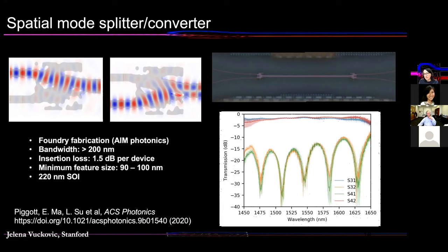When we received chips from the tape out and measured, we saw 3 dB loss total. So 1.5 dB per device. And again, the discrepancy comes from the fact that minimum features in a foundry were about 100 nanometers and not 80 nanometers the way we designed. But nevertheless, this is still an excellent performance and a very useful device that you could use to capture two input modes or two polarizations.